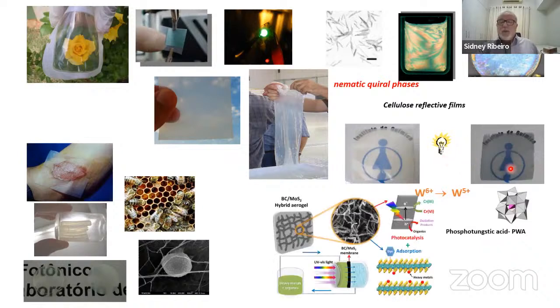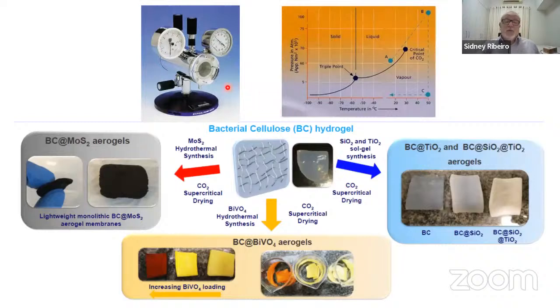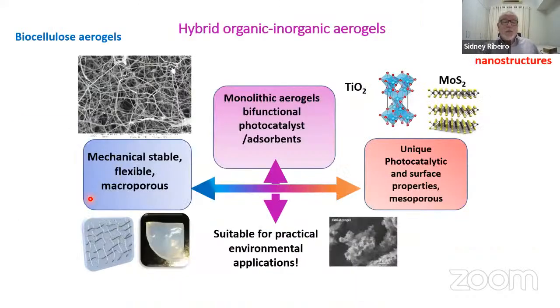Or you can prepare aerogels and use the membranes so obtained in water decontamination. What we are doing is supercritical drying, CO2 supercritical drying. By doing that, you will obtain new aerogels and you can incorporate semiconductors that are used in photocatalysis. So we can do that with titanium oxide, bismuth vanadate, or molybdenum sulfide. So these are new materials where we have the good things of both worlds.